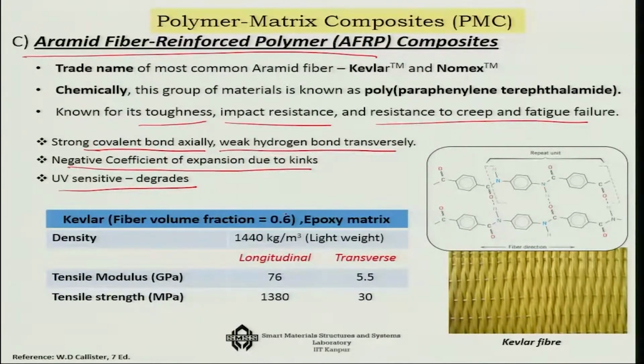Now Kevlar with a 0.6 volume fraction, you can see that the density is only 1440, so it is even lighter than CFRP in some cases, and definitely lighter than GFRP. And if you look at the tensile modulus, close to aluminum, 76 GPa in the longitudinal direction, while transverse it is pretty weak, only 5.5. The tensile strength is 1380 MPa in the longitudinal direction and 30 MPa in the transverse direction.